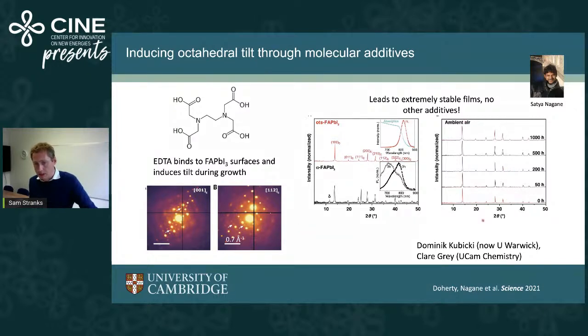What it leads to is an extremely stable and phase-stable film. This is looking at the X-ray diffraction pattern of films left in ambient air for many thousands of hours, and we don't see any formation of hexagonal phases in these films, as long as we've got the tilt. But if we don't have tilt, these form within seconds. So this pure form of formamidinium lead iodide without the tilt, we see these delta phases forming very, very rapidly. So this really does lead to much, much better stabilization of the films.